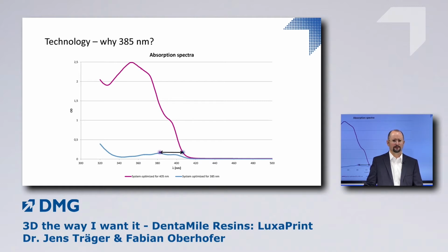At first glance, it seems they are very much different, but we need to take a closer look, first at the wavelengths the printer uses, which is 385 and 405 nanometers. If we look at the 385 nanometer material, we see that at 405 the absorption is very low, making it not suitable for irradiation with 405 nanometers. So we need to bring that absorption up at 405 nanometers if we want to have a material suitable for that wavelength, and therefore certain additives are needed.